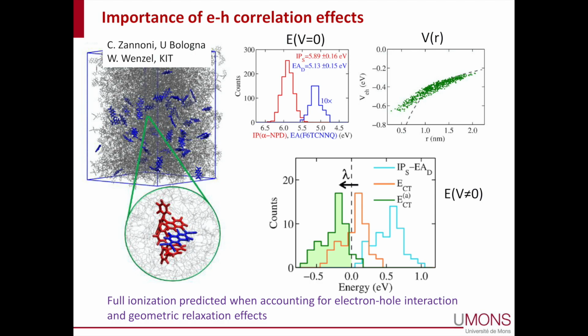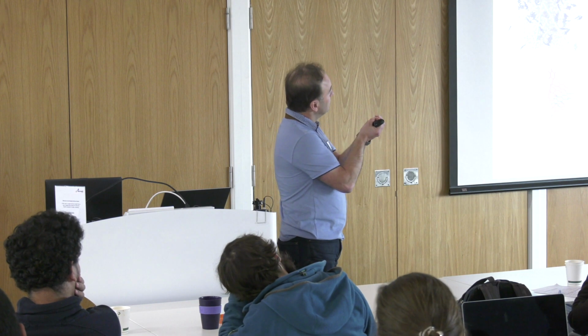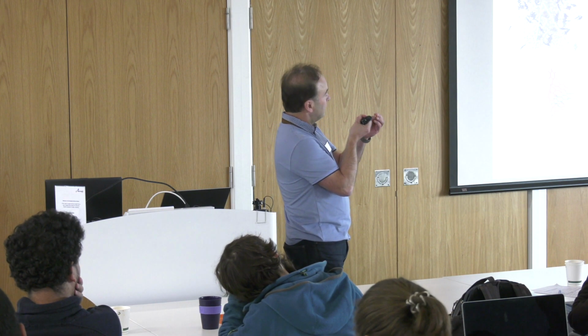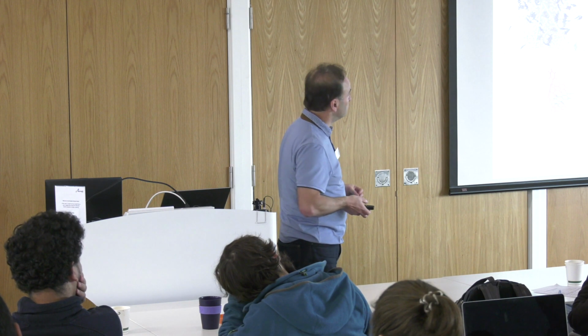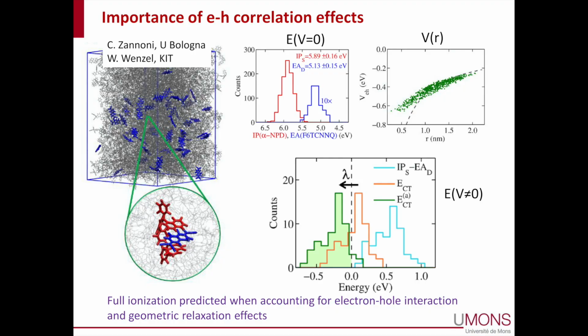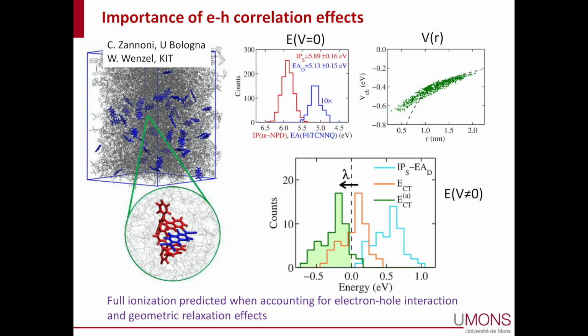Well, yes and no, because there's one thing that we're ignoring in this picture, and that is the fact that once you ionize the host, you ionize the dopant, you're left with a hole sitting on the pentacene and an electron sitting on the acceptor, and those are Coulombically bound. And so if we take into account this Coulombic binding, which is substantial, and we take into account the polaronic effect, so the relaxation of the nuclei around the charge, then we end up with a situation where there is full ground state charge transfer.